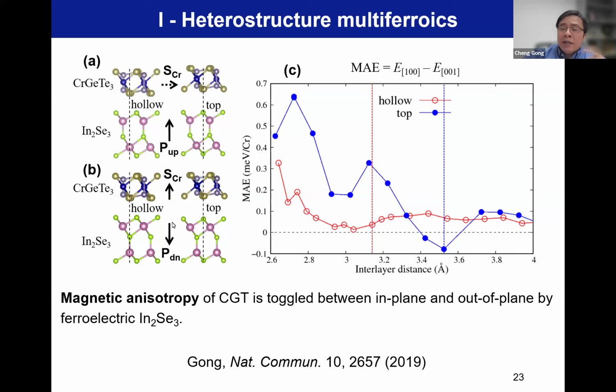This is very interesting. Given you have a ferroelectric material, it allows you to use a small voltage, just the coercive voltage, to flip the ferroelectric polarization. That means the ions are moved. Once ions are moved, of course, it can cause a substantial effect in the magnetic property. It's not like just electrostatic doping or an electric field. Now ions are moved, and then they will bond to the magnet and cause a strong effect. Such an interfacial effect is strong in many systems.